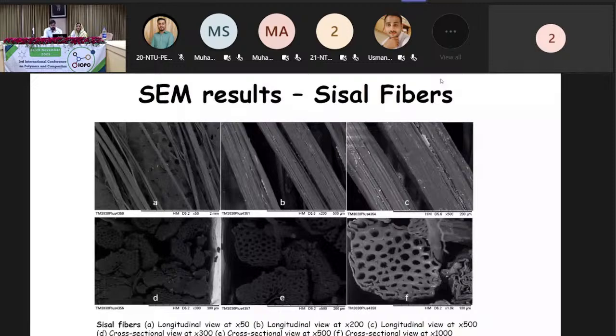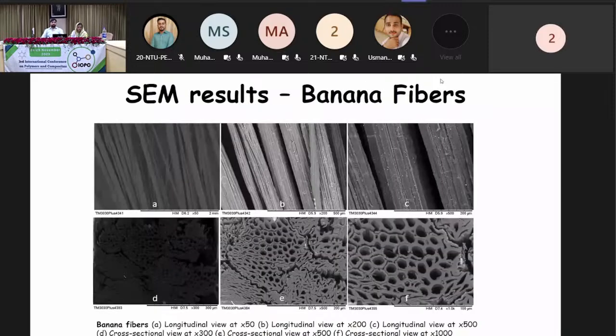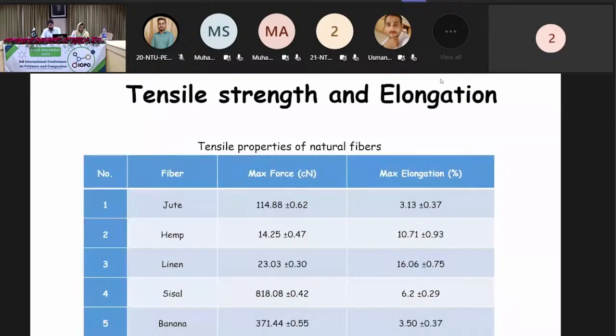Regarding sisal fibers, they are straight, cylindrical, and have a hollow structure. Banana fibers are also straight, cylindrical, and have a hollow structure. Banana fibers are a more practical solution for better moisture management and air permeability due to the surface grooves, as seen from the scanning electron microscopy results. However, owing to their roughness, banana fibers cannot be used as a substitute for linen fibers in clothing fabrics.